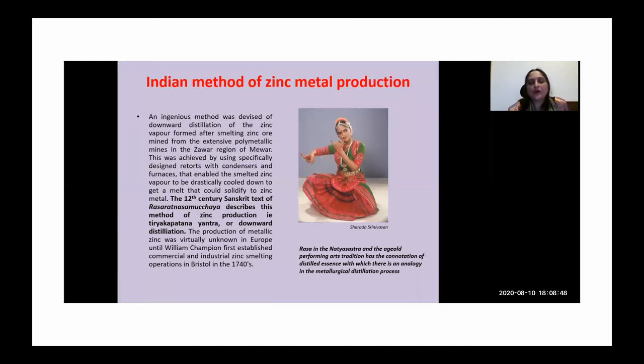And it's also interesting that there's a lot of literature in terms of descriptions of the accounts of zinc smelting. The 12th century Sanskrit text of the Rasaratna Samuchaya describes this method of zinc production as Thiryak Patana. And there's also talk of the Thiryak Patana Yantra, the apparatus for the downward distillation. And there's a lot of correlation as well. For instance, a retort is described as being aubergine shaped and so on, which is a good description, and the use of salt for sintering and so on. So a lot of studies have been made on the refractory materials using thin sections and so on by Paul Craddock and the team. And they've actually found a lot of good correlations with the textual references. So it's quite an interesting example of how there is a whole body of textual evidence as well to support the development of this indigenous method of zinc smelting.